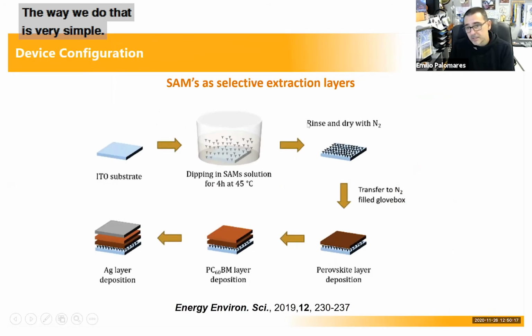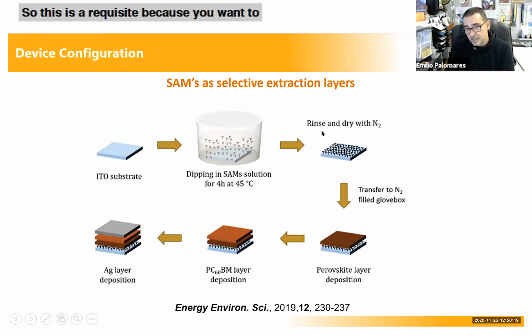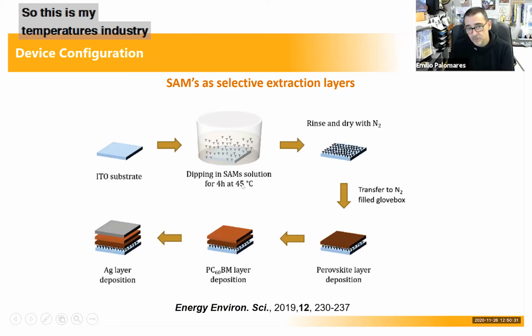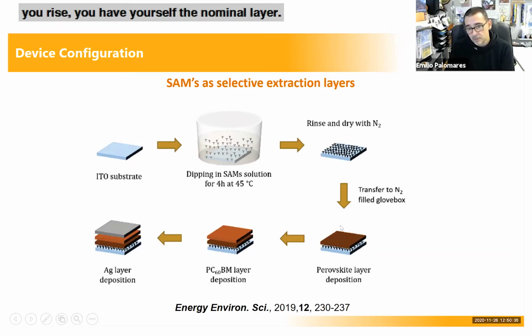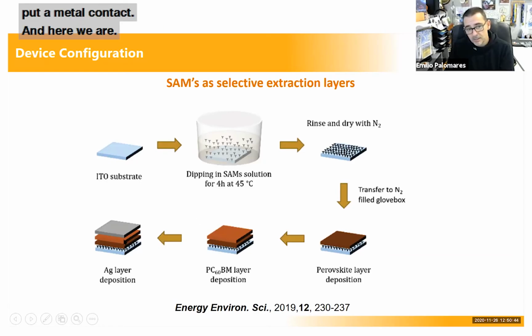The way we do that is very simple. This is a requisite because you want to do this as close as possible to industry, to make life easier for it. So you take ITO, you dip the ITO in a solution at 45 degrees. So this is mild temperature, industry can afford it. 4 hours, you rinse, and you have your SAM as a monolayer. You then build the perovskite layer on top. You evaporate the C60 and then you put the metal contact, and here we are. We have the solar cells ready to be measured.